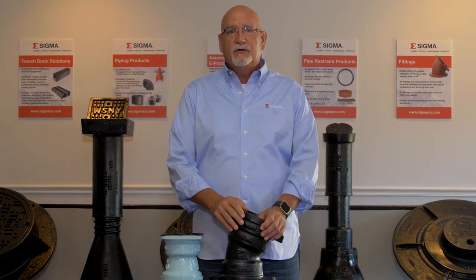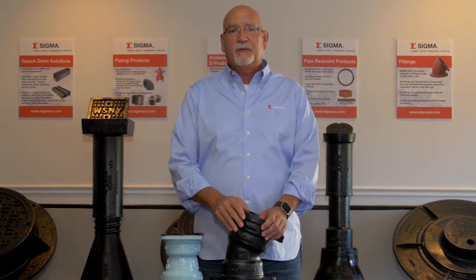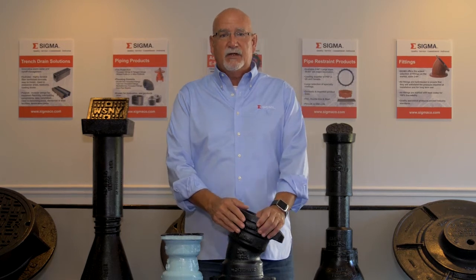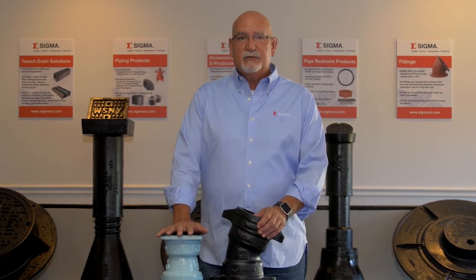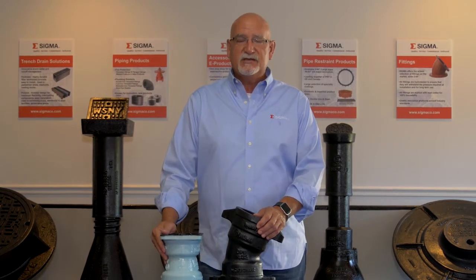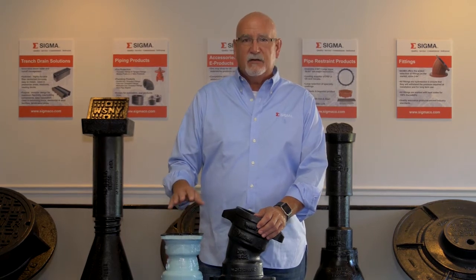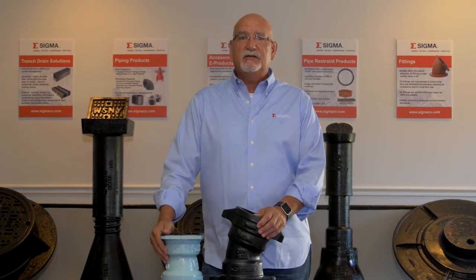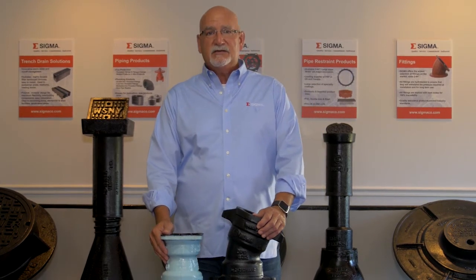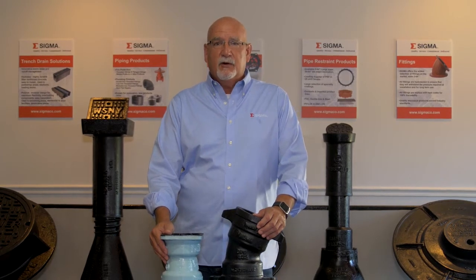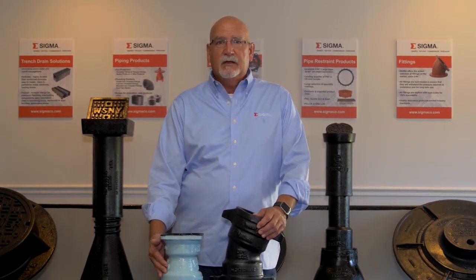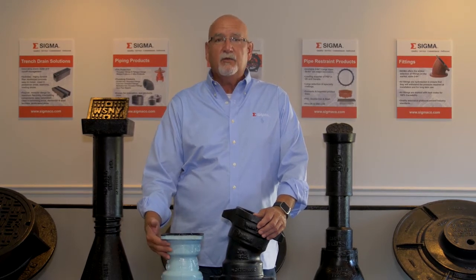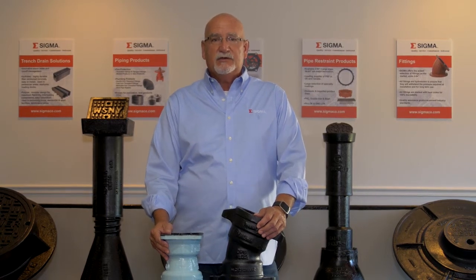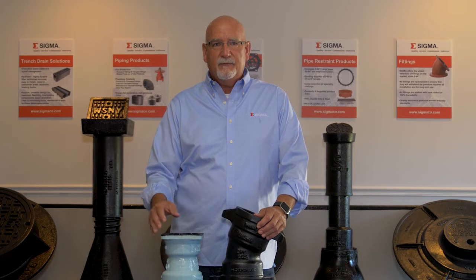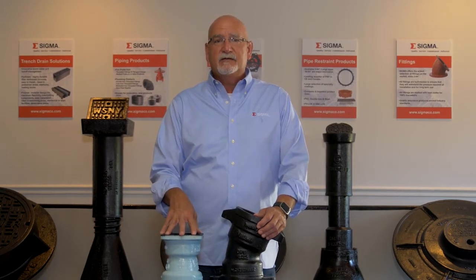And finally, there's the combination of a sacrificial coating and a barrier top coat to give you the best of both worlds. And Sigma has developed a product that we're branding as Sigma Safe. This is an example of what a Sigma Safe fitting looks like. This is a standard fitting that has been coated with a Tnemec zinc primer that meets the European standard for the number of grams of zinc per square meter of the coated surface on the exterior. That primer is allowed to dry, and then we coat it with a barrier top coat of another Tnemec material that provides as good a protection as FBE.